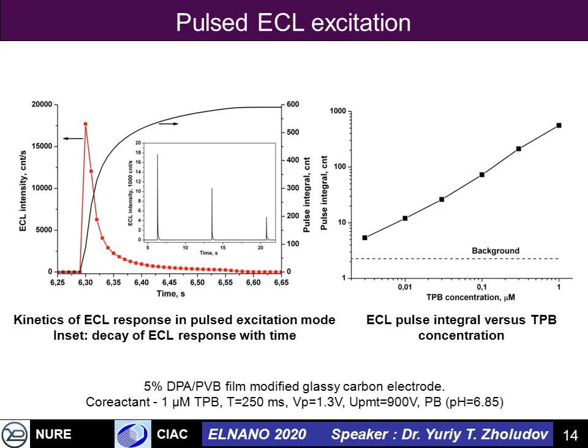On the right picture, you can see the dependence of this pulse integral intensity versus the concentration of coreactant. The coreactant concentration on this slide is given from less than 1 nanomole up to 1 micromole. So the system is extremely sensitive for TPB detection.